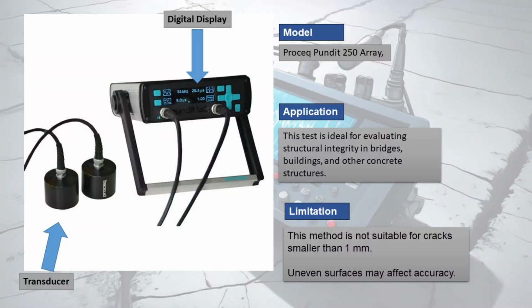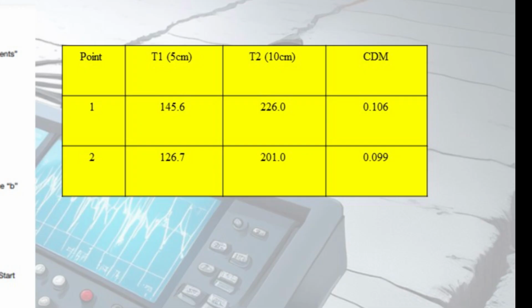The limitations for this test: this method is not suitable for cracks smaller than 1 millimeter. Uneven surfaces may affect accuracy. This is the result of the experiment for point 1 and 2. Based on the result, the crack depth is not severe.